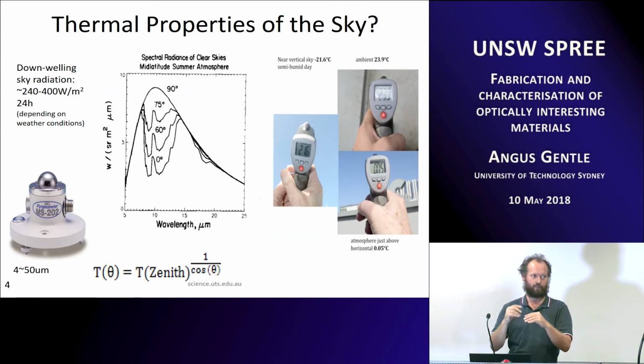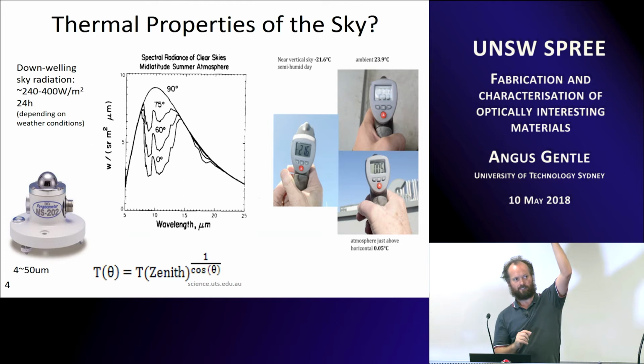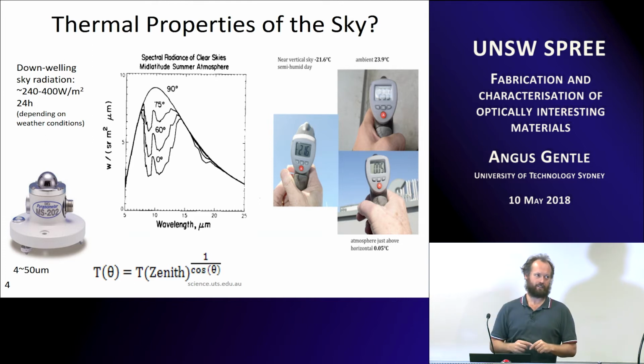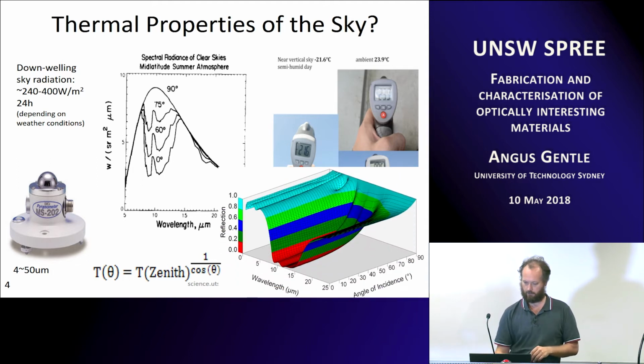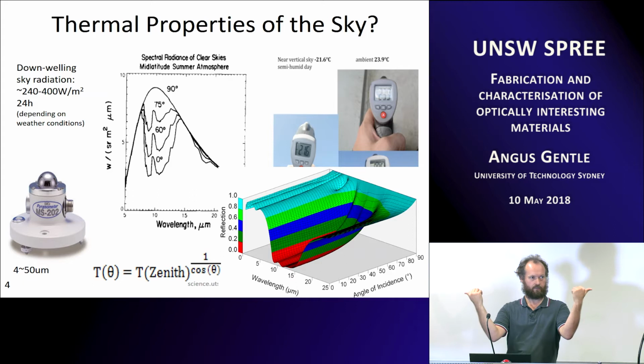So if you want to look at it spectrally, you've got to sum it up over the distance. You can't just say it's that way and it's this temperature, which is what some people do. If you have the transmission spectra of how much goes through at different angles, you can get the transmission at the zenith, and then a simple equation works out how much at other angles. Then you can look at how much is being absorbed by your sample at each of these angles, because you can measure the reflectance of whatever surface you have. So if you don't want to do the lumped hemispherical emittance, you can calculate at each angle and sum it all up. Because you've got this pattern, you want to emit more straight up and emit less further out over certain wavelengths,